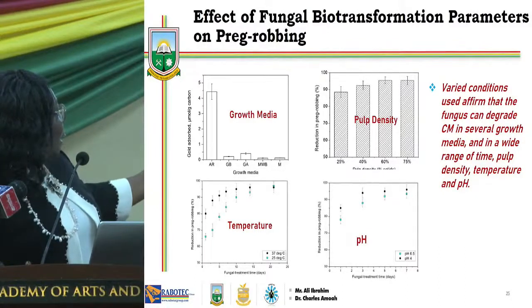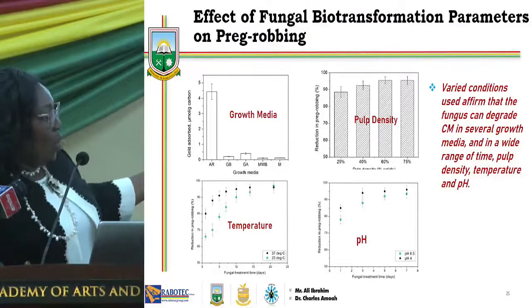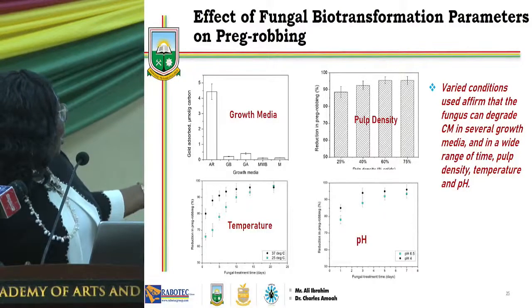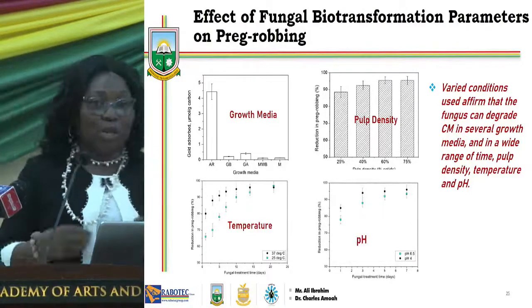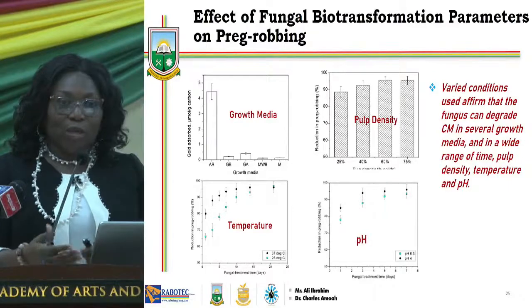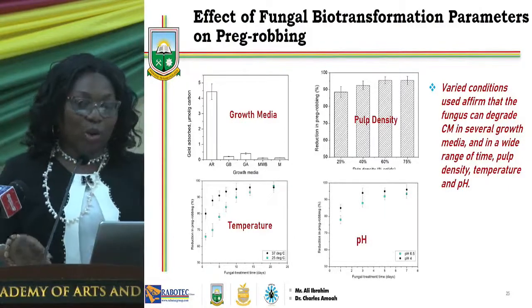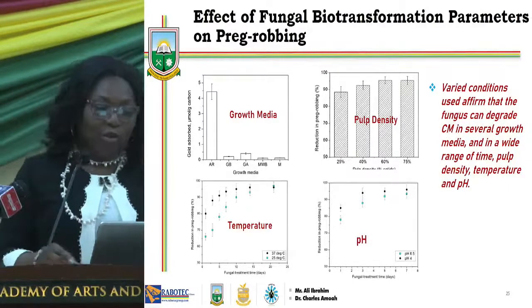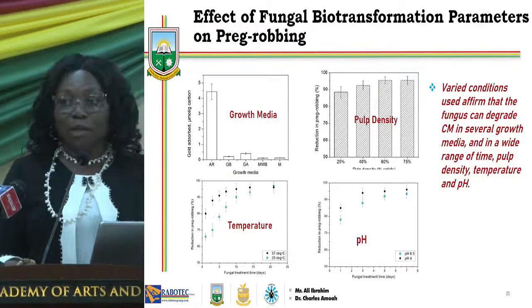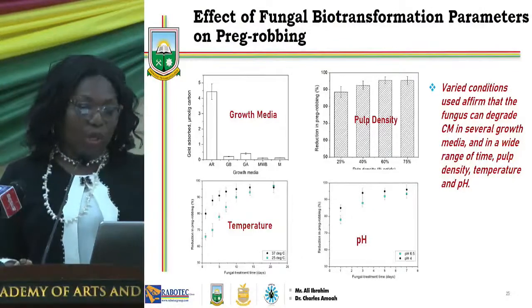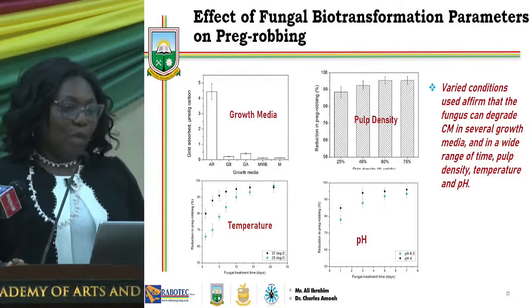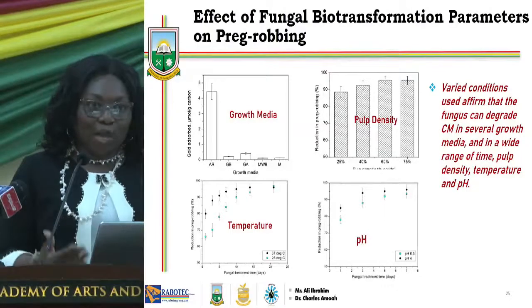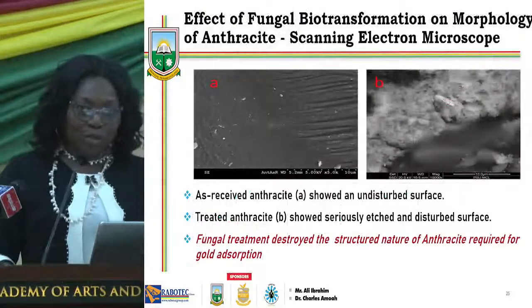Then we have pulp density of the media, pH and temperature. So when we incubate the anthracite with the Phanerochaete chrysosporium under different conditions, the fungus is still able to act on the carbon. So the fungus has been able to reduce gold absorption.